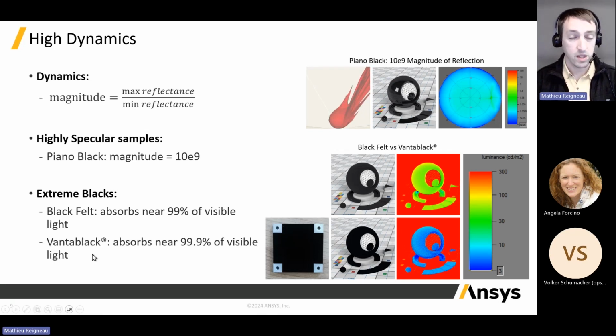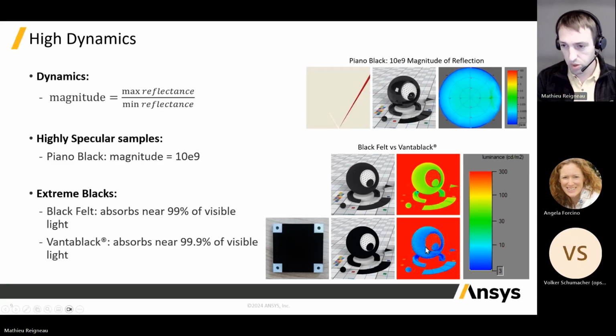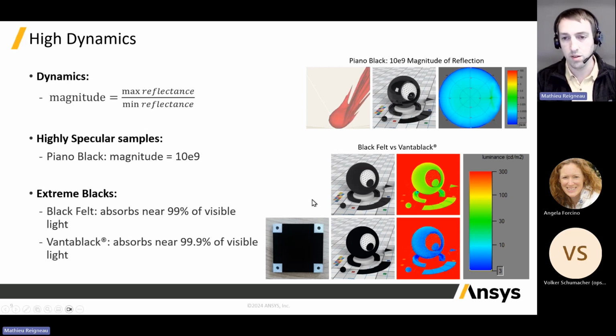And to be compared with the Vantablack, which is one of the references, but absorbs more than 99.9% of the visible light. Knowing it is black is fine, but when you are working on stray light and trying to capture as much light as possible, what is important is not the amount of light that is absorbed, but the amount of light that is not absorbed. And that's where, through an accurate measurement, you're able to see how much light and how this light will be absorbed and not absorbed on the material. And so a high quality scanning system can achieve this and deliver, through the simulation, correct behavior on using one or another material for absorbing stray light.